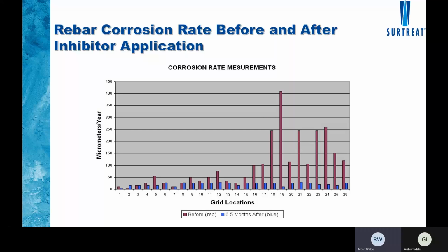One, that the corrosion rate is not uniform, but we can see where we have these corrosion hotspots in spots starting at 18 on up through 26, while 1 through 15, we're staying pretty much below 50 micrometers per year. But then we have hot spots going all the way up to 400 micrometers per year. And it's this area where we had the maximum loss of steel and damage. The important thing to see here is that through the application of TPS2, we've quenched these corrosion hotspots.